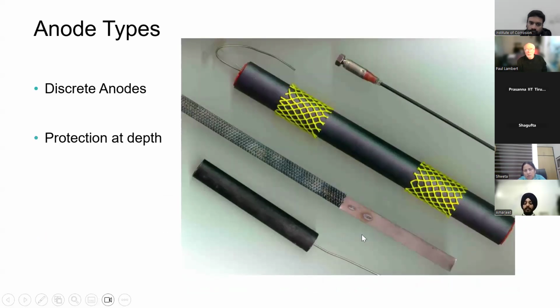Other things, discrete anodes. If you can imagine, you can drill a hole and you can insert something that is also going to act as an anode. You can work in 3 dimensions. You can make them longer, deeper, more close together, further apart, and really model the current that you're distributing for optimum effect. These are just some various. These are a bit old now, but the top one, top right, is a coated titanium. The middle one is titania, so it's titanium oxide. Works without any coating because it is already, as it were, oxidized titanium. Works very well. And then we've got a couple of coated titanium alternatives below that.